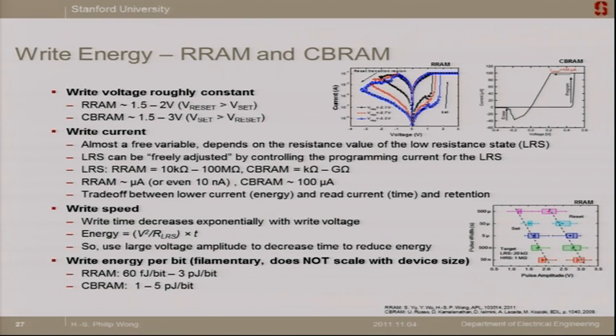Now, obviously, there's a huge trade-off between lower write current and the read current that's available, and the retention time. Let's say you have a write current of a microamp. If you don't want to have a read disturb, then the read current has to be substantially lower than the write current. Otherwise, when you're reading, you write the cell, and that's no good, right? So typically, the read current has to be at least 10x, hopefully 100x smaller than the write current. So if you have 1 microamp of write current, then your read current has to be like 10 nanoamps. Then that means it takes a very long time to read the cell. Then the cell will be very slow, right? So that's one trade-off in the read time, okay?